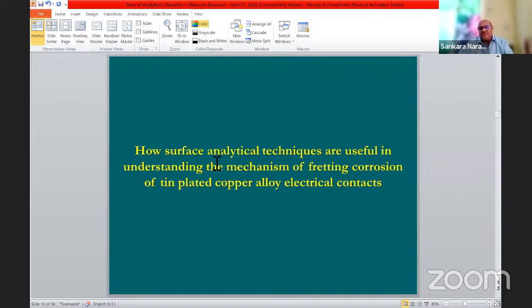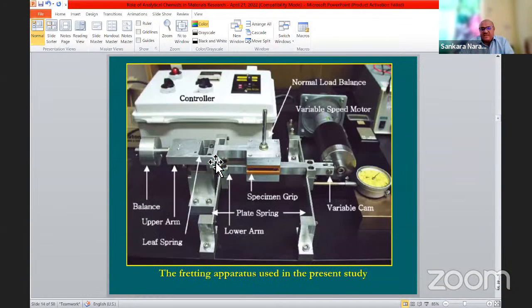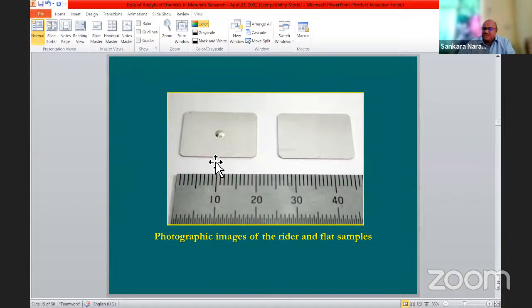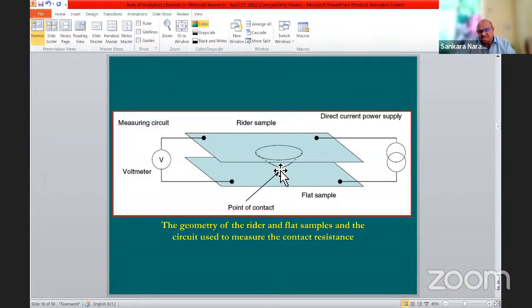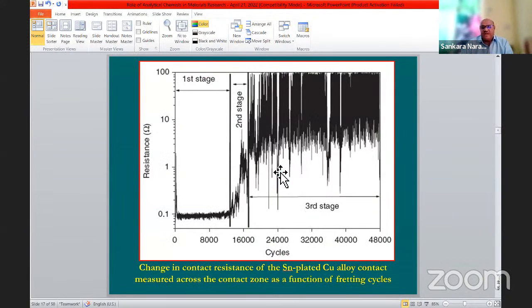So I will explain it. We have developed a simple setup to study the fretting corrosion behavior in the laboratory. This work I did in Korea. Okay, this is the sample, a copper alloy brass sample coated with tin, and this is a flat sample, and this is the rider. We made a small punch to create a ball-on-flat contact configuration. So this is the arrangement. It's a flat sample and then the rider sample. During the small amplitude vibration, there will be movement, and the tip of that rider can remove the tin plating. We connected it to a circuit and measured the resistance during this. This is the way we have done it, up to 48,000 cycles.